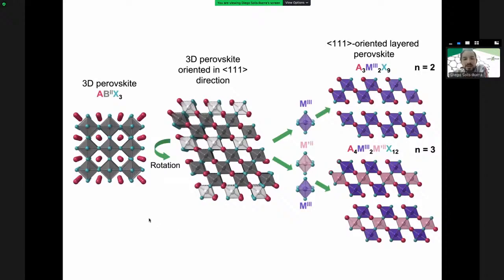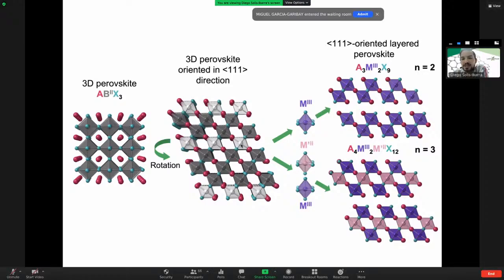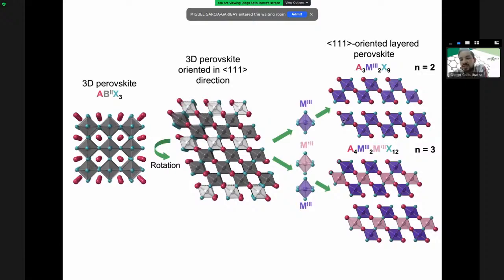So here's another way of looking at them: introducing vacancies and replacing them with different elements. And what this generates is these layered perovskites. You generate layers by changing the charge on the metal. So this is something that is done in situ. You don't have to do much work. You pretty much just put the reagents there and you get your layered material.